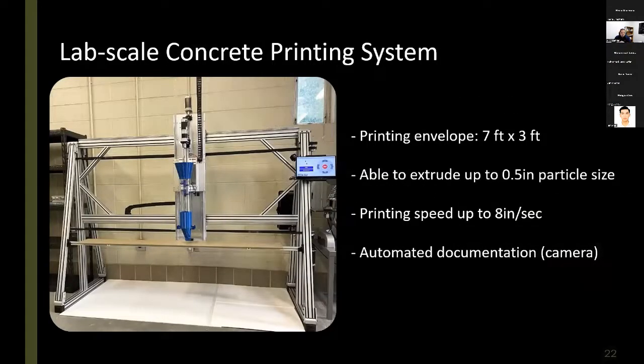And of course, for our printing experiments, we needed a printer. So this is the linear concrete printing platform, which I developed for my PhD students. It has a build envelope of 7 feet by 3 feet height, and is able to handle aggregates up to 1/2 inch maximum size, printing at a speed of up to 8 inches per second. And we have some documentation cameras which are automatically triggered when we run an experiment.